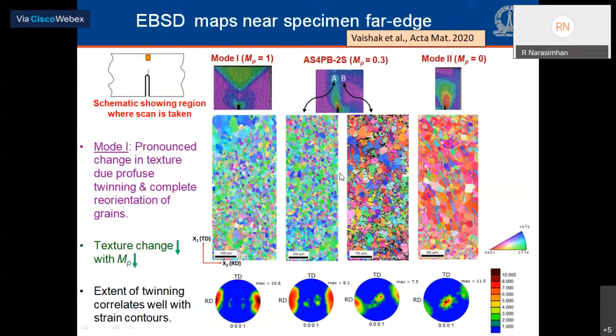Again, for mode 1, mixed mode, and mode 2 case. And I have also affixed the von Mises strain contours on the top. If you compare the 3 different cases, in the mode 1 on the left side, you see again almost all grains are completely reoriented. And the texture shows massive changes. The bottom pole figure shows basal to prismatic change in the texture.